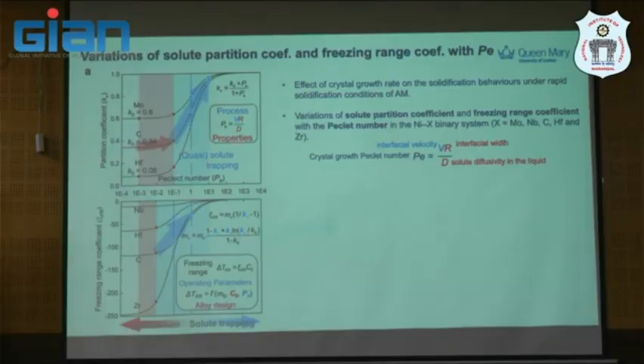It's going to non-equilibrium. And this is actually the blue one related to your, this is not your scan velocity, no. This is due to the scan velocity or energy contributing to the velocity in the liquid. And this diffusivity here will promote this zone. So you get trapped in this zone. Or it is a freezing range coefficient, because if you have very rapid solidification, this one will actually promote or change your freezing range as well under printing.